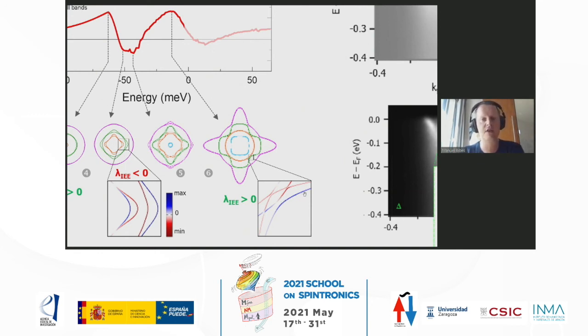So you see, for instance, here we have a large dark blue contrast, but here we have almost zero spin here. This means basically the expectation value, if you wish, the length of the arrows in these sketches of the curling contour, the length of the arrow is almost zero. There's no arrow. And of course, then this gives rise to large conversion efficiency because one band is contributing in full and the other is not contributing in the other direction. So there's no compensation by the other band as you always have when you work with Rashba. In Rashba, you always have one band compensating for the other.